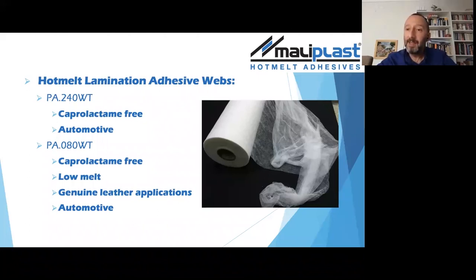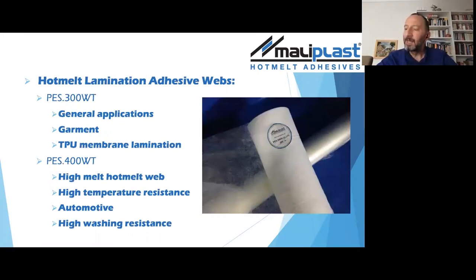Then we have got our PA080WT. It is a low melt product. Actually, it gives very good performance with genuine leather lamination applications, especially for the automotive application. There, the genuine leather is sensitive to the heat, so in order not to lose the gravure, the design on the surface of the leather, there might be a requirement for a low melt polyamide hot melt adhesive. Now I would like to pass to polyester hot melt webs.